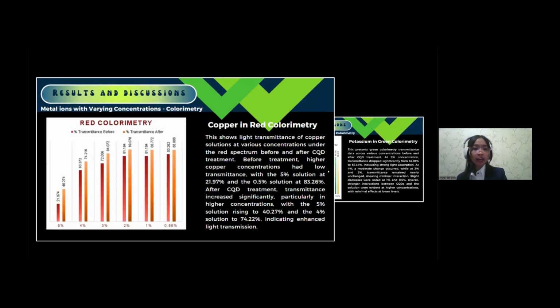Here we have a figure that shows how copper solutions of different strengths let red light through before and after adding CQDs. Before adding the treatment, the stronger copper solutions absorbed more light. For example, only about 22% of red light passed through the 5% copper solution, while the weaker 0.5% solution let